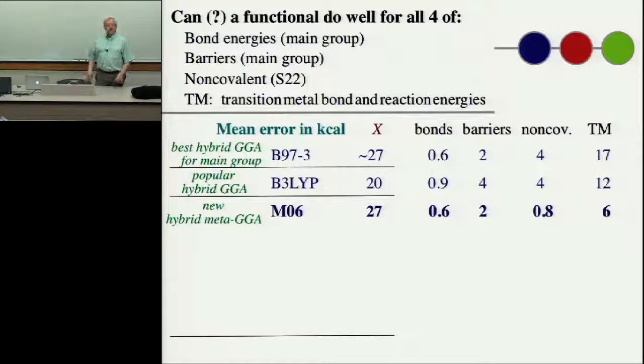But if you would do this anharmonic shift accurately, you'd get a very similar conclusion, either way of doing the calculation. So we feel that the proper thing to do is to have a calculation that doesn't have the vibrational effects in, agree with the potential surface that doesn't have the vibrational effects in. Some people say, well, I can't really afford to do it right, so I'd like to build in errors. I'd like to build in so that my functional, without putting in the quantized zero-point vibrational motion, predicts the experimentally observed structure. But we think that that game will get you only so far. It's building in cancellation of errors, so we don't like to do that.